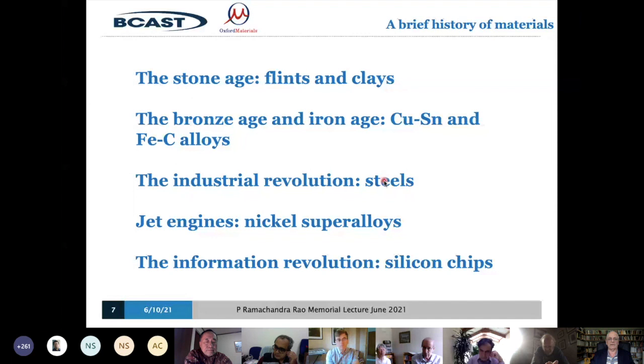Steel is not really made properly until the 18th and 19th centuries. And as many people in the audience know, irons have more carbon in them. They're less pure than steels, and steels are a reduced form of iron where you oxidize back out some of the carbon. So instead of having a few percent of carbon, you have 0.1, 0.2, 0.3, 0.4, up to about 0.8% of carbon in steels. And it's a much more usable material in the sense that it combines that ability to have forming capability, which I mentioned already, which all metals have because they're relatively soft, together with the hardness and strength. And by controlling that carbon, you get wonderful new materials which drive and underpin the Industrial Revolution.